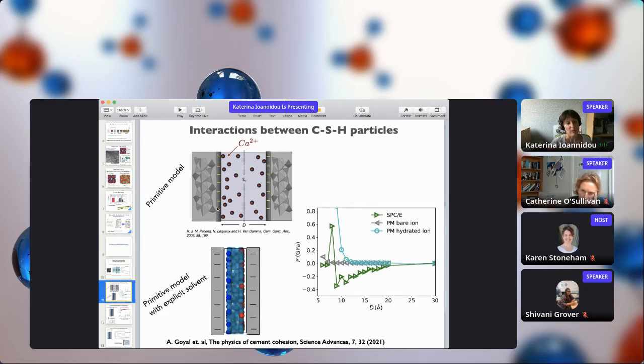Having a primitive model here will give us the curve that we see, the gray curve. Here we are measuring the pressure between these two charged planes of CSH as a function of the distance. We see that the pressure we observe is very low with the primitive model. The primitive model is a mean field approximation, so this is what we are expecting to get.